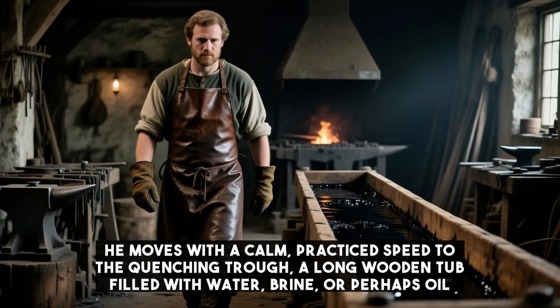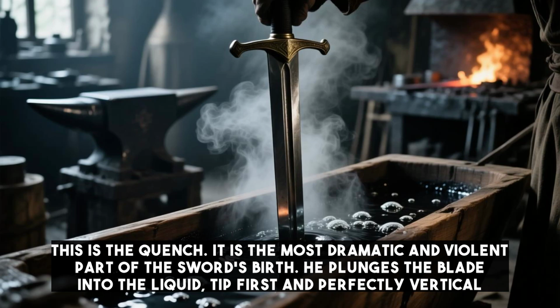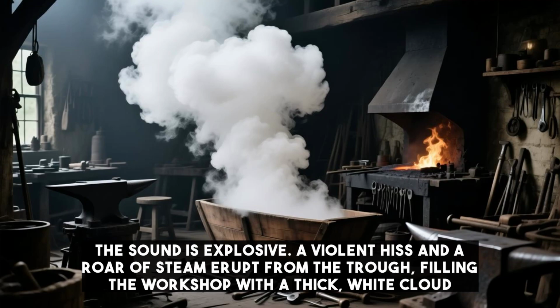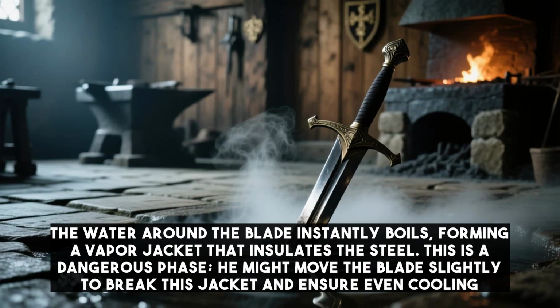He moves with a calm, practiced speed to the quenching trough, a long wooden tub filled with water, brine, or perhaps oil. This is the quench. It is the most dramatic and violent part of the sword's birth. He plunges the blade into the liquid, tip first and perfectly vertical. The sound is explosive. A violent hiss and a roar of steam erupt from the trough, filling the workshop with a thick, white cloud. The water around the blade instantly boils, forming a vapor jacket that insulates the steel.